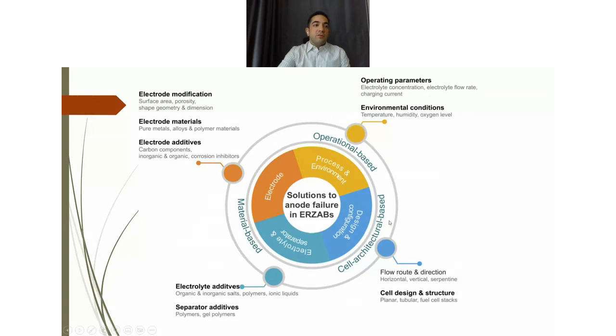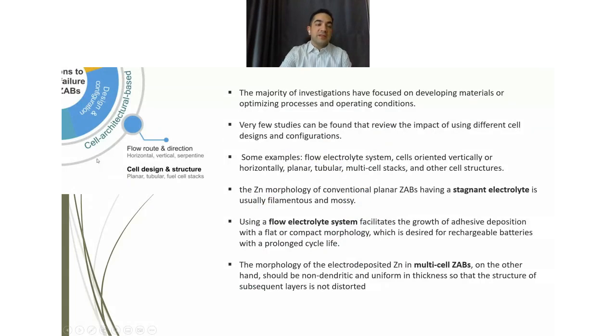solutions. So, for beginning, we start with cell architectural-based solution, which mostly highlights the solutions that use different cell design and configuration to overcome this anodic issue, like introducing flow batteries or using different orientation of the cell. Some instances are flow battery system, cell oriented vertical or horizontal, using planar or tubular cell, or using multi-stack cell instead of a single cell. And regarding these issues, it mostly highlights the evolution of each of these cell configurations on the zinc morphology on the zinc anode.